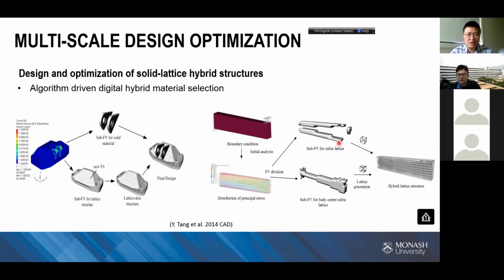For example, on the top and the bottom, because the principal stress direction is along this beam, we use this type of cubic lattice cell. And at the middle, there is shear stress, so we use a body-centered cubic lattice structure. So we use a different type of cell topology in a different region to further enhance the mechanical properties of the designed structures.